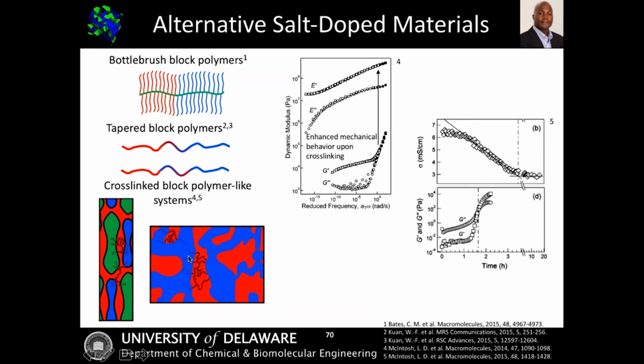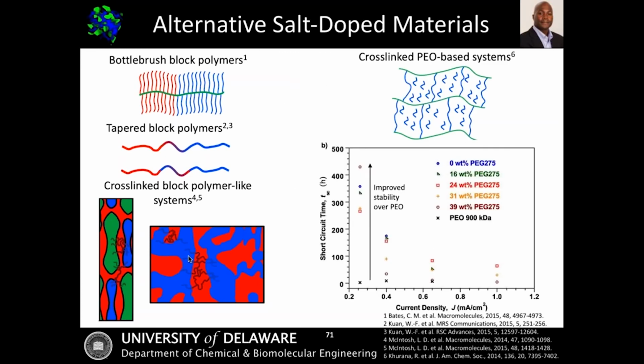One of the nice things about this is that they didn't actually have to make a traditional block polymer. They actually used a polyethylene oxide as basically a seed material, and then they used a styrene divinylbenzene mixture, which was able to polymerize off of that polyethylene oxide and phase separate simultaneously, which allowed them to form a very nice co-continuous structure. Even though it didn't have long-range order, it still showed an increase in performance in terms of conductivity.